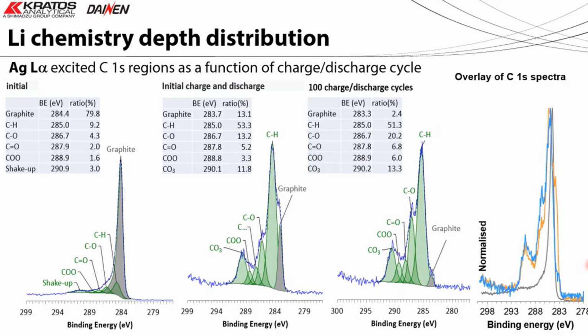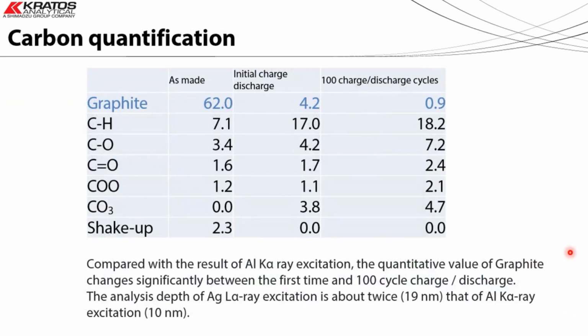So we're seeing, let's scroll down. Yeah, the biggest observation there is again the attenuation of the graphitic signal. Even though we're sampling deeper into the material, we're still looking at the same core level. So that has higher kinetic energy, greater sampling depth relative to the aluminium. We're still attenuating that graphitic carbon, implying that we must be generating a relatively thick SEI layer.